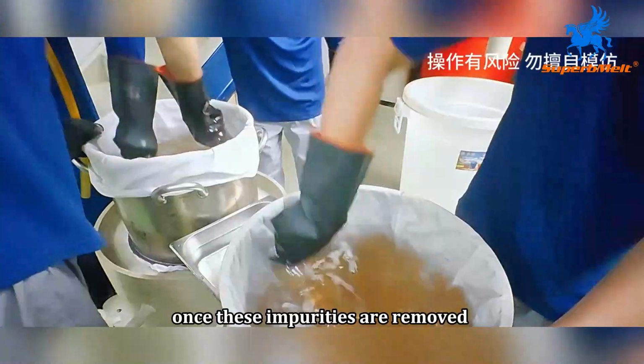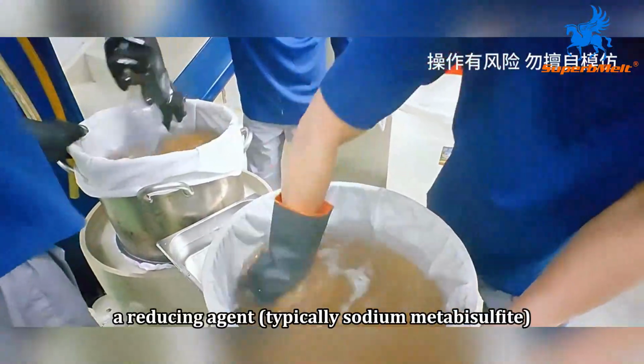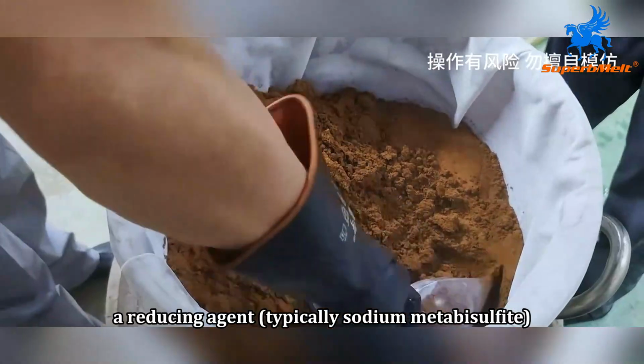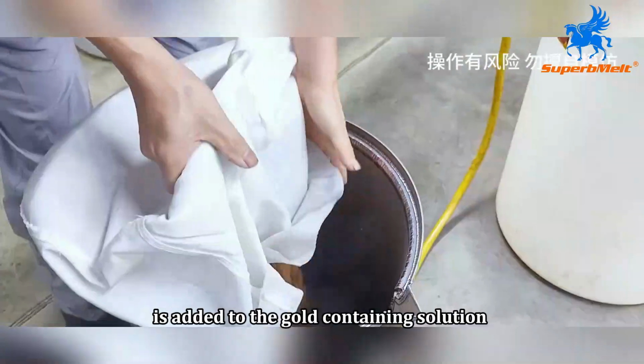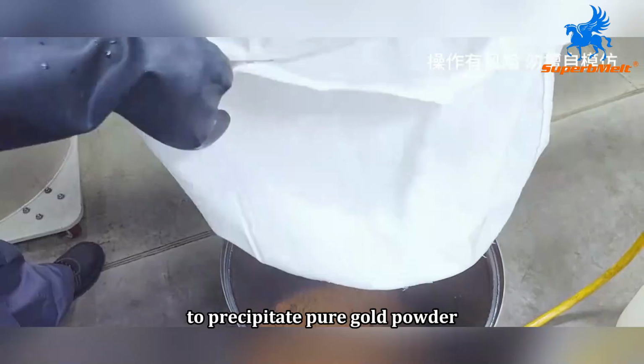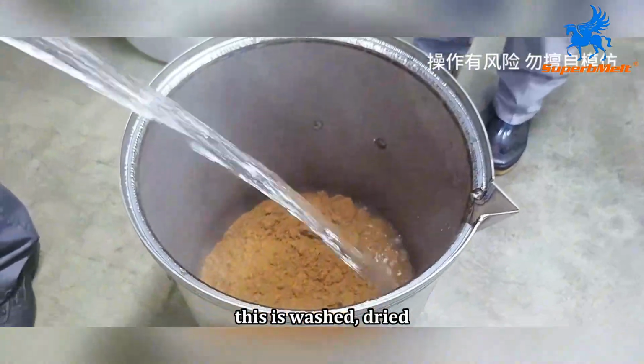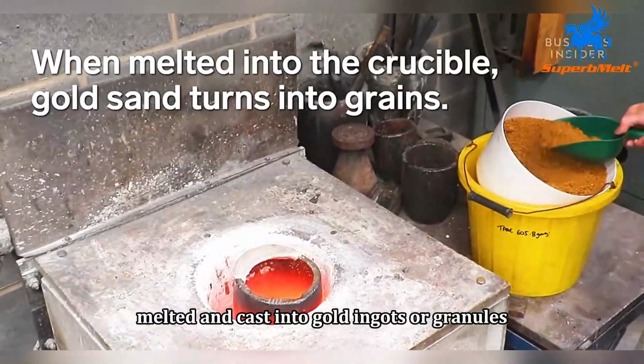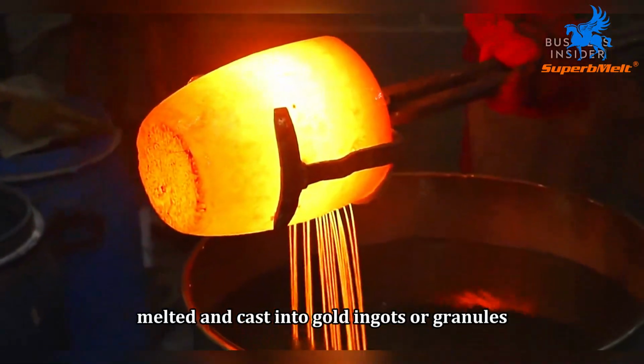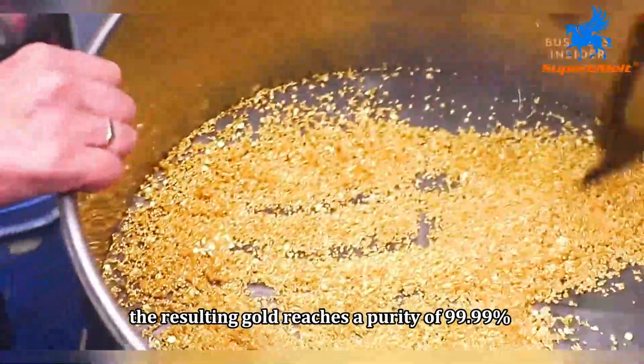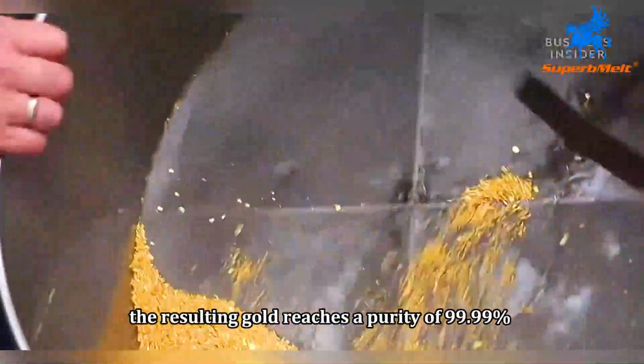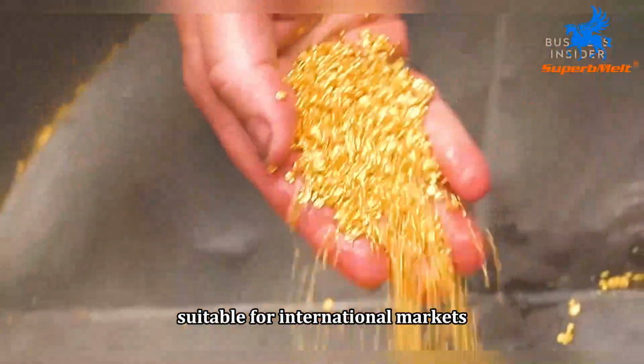Once these impurities are removed, a reducing agent, typically sodium metabisulfite, is added to the gold-containing solution to precipitate pure gold powder. This is washed, dried, melted, and cast into gold ingots or granules. The resulting gold reaches a purity of 99.99%, suitable for international markets.